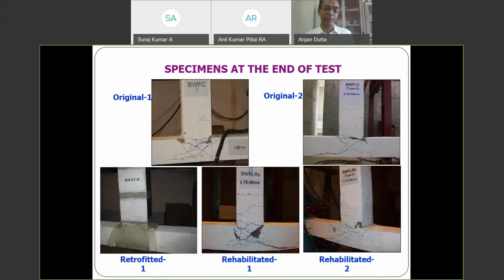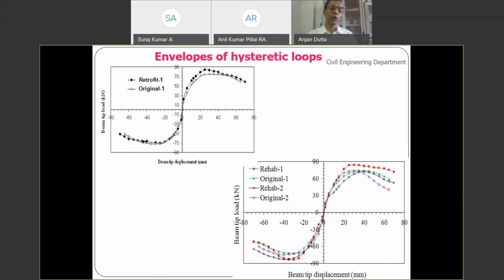After this, earlier we had tested all the retrofitted specimens. Now we have tested again all the rehabilitated specimens. So we have all the pictures for the original control specimen, retrofitted specimen, and rehabilitated specimen, and they have all now failed in the desired mode. And finally, you see some of these plots, load versus displacement curve, and you see the retrofitted specimen is having more capacity than the original specimen, that is the control specimen. And rehabilitated specimens are more or less similar to your original specimen. This is the target. In fact, sometimes you find the rehabilitated specimens are better, as epoxy is having very high strength.